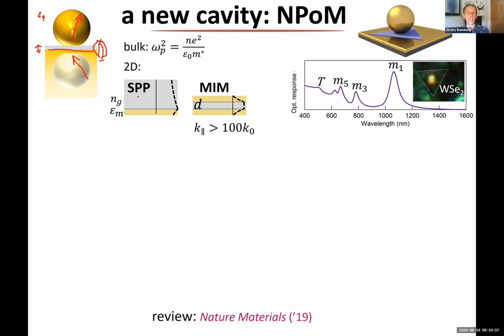Okay, so what I'm going to do is try to explain why it's so good to confine light in this sort of region between two metals. We already know that there's a plasma frequency in a bulk metal, which is what you learn as undergraduates, and which depends on the square root of the electron density and the effective mass. We also know that we can trap light into a two-dimensional plasmon on a bulk metal surface like this. That plasmon's penetration depth into the dielectric above the metal is smaller than the wavelength of light, but not that small. It's only when we make this metal insulator metal structure that we can confine light incredibly tightly.